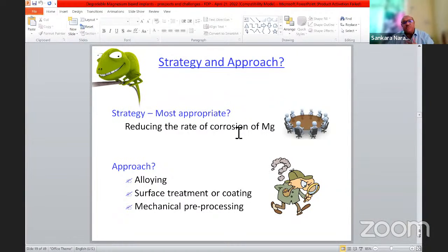So what is the most appropriate strategy? It is to reduce the corrosion rate of magnesium. How can we do that? We can do it by adding alloying elements, by surface coating, or we can do mechanical pre-processing like surface mechanical attrition treatment or ECAP, etc. Alloying is a good choice. It can increase the mechanical strength, no doubt about it. But you cannot use all the alloying elements because we are putting it in as a degradable implant. So it is going to dissolve in the human body.